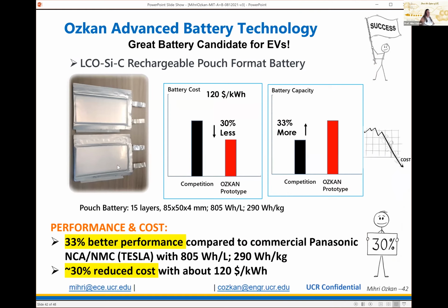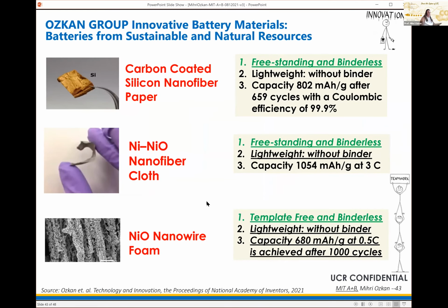We also went ahead and made 15-layer scaled-up batteries here. The battery cost was about 30% less, and the capacity was around 33% more compared to Tesla's batteries. We went through the elimination method, and we eliminated the binder and current collector, and we used carbon-coated silicon nanofiber paper, or nickel-nickel oxide nanofiber cloth, or nickel-nickel oxide nanowire foam. And again, template-free and binder-free, we demonstrated a successful battery.